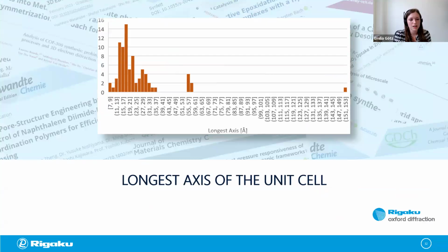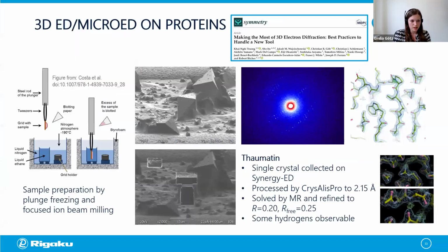Another interesting thing to look at are the longest axes that have been published with the Synergy-ED so far. We can see that the largest amount is below 30 angstroms, which is mainly due to the amount of small molecules measured, and then in the higher range also MOFs. And then there is a peak at around 57 angstrom, which is clarithromycin. And then we have one all the way back there, which is a protein. Because, of course, it is also possible to do a structure solution of proteins with the Synergy-ED. And we have shown this exemplarily on thaumatin in the paper by Zhuang et al.